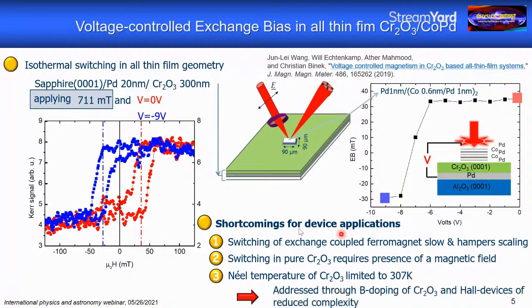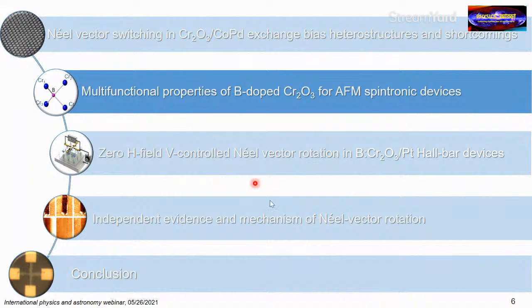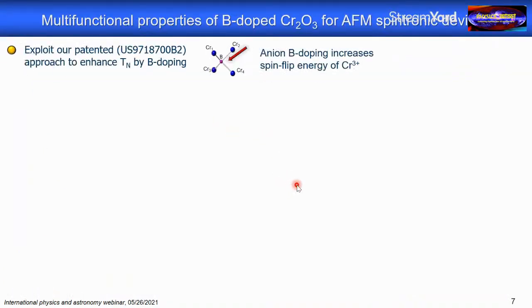And that's what led us to the idea that we have to change the system. The first thing was trying to dope it with something to do that. And that's what I want to report on next. So we started out with boron doping of this chromium oxide with the goal to increase the antiferromagnetic ordering temperature. Again, that was a theoretical idea that came from our colleague Kirill Belashenko, who did first-principles calculations and found that by replacing the oxygen position with boron, you can change the exchange interaction between the chromium ions, and that in turn changes the antiferromagnetic ordering temperature in our favor, making it higher.